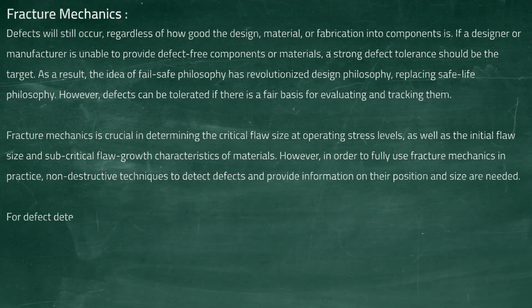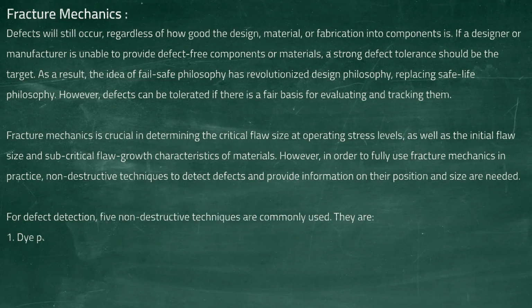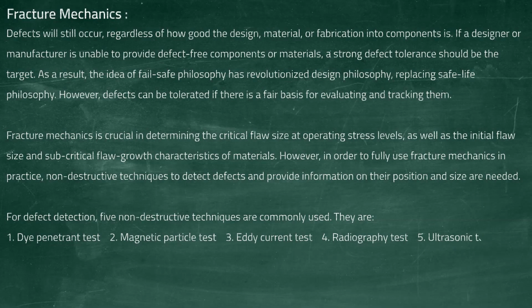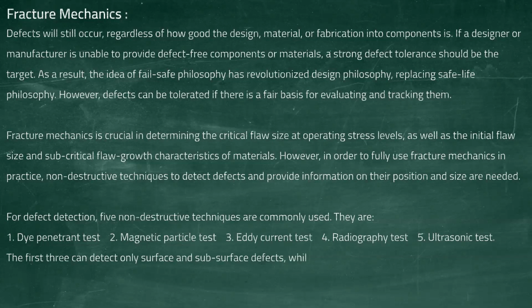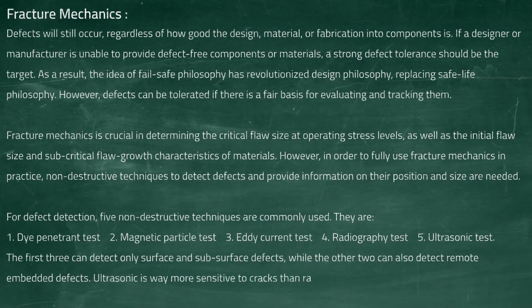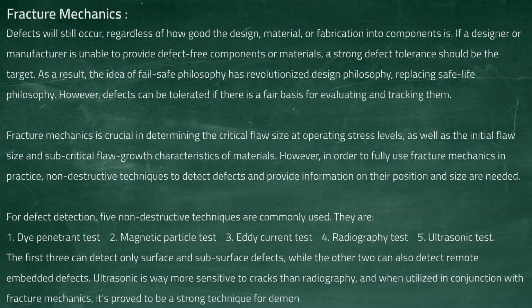For defect detection, 5 non-destructive techniques are commonly used. They are dye penetrant test, magnetic particle test, eddy current test, radiography test, ultrasonic test. The first 3 can detect only surface and subsurface defects, while the other 2 can also detect remote embedded defects. Ultrasonic is way more sensitive to cracks than radiography, and when utilized in conjunction with fracture mechanics, it's proved to be a strong technique for demonstrating component integrity.